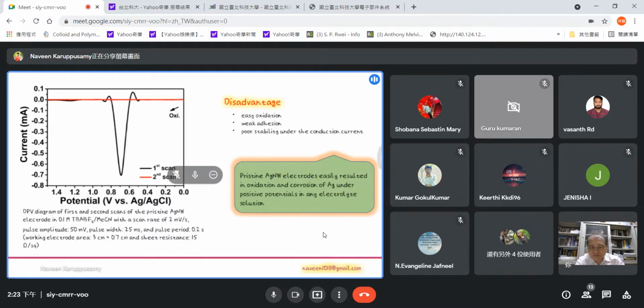This is the DPV performance with the pristine silver nanowire. At the first scan, we can clearly see the oxidation peak observed at 0.7 potential. At the second scan, no oxidation peak is observed. This is the major disadvantage of using pristine silver nanowire: easy oxidation, weak adhesion, and poor stability under conduction current. The pristine silver nanowire electrodes easily result in oxidation and corrosion of silver under positive potential in any electrolyte solution.